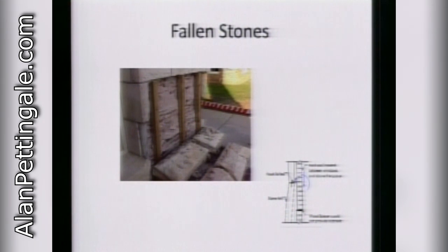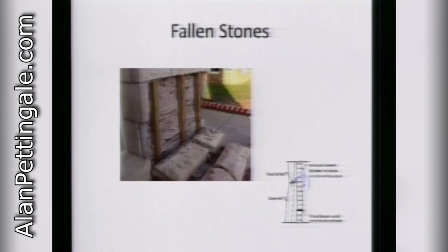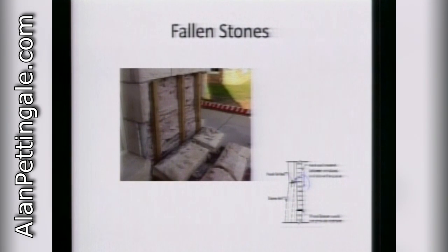The problem that happened some years after the reconstruction was that some of these stone water table elements fell off and had to be shored up. You can see from this picture that there was a cast stone anchor that failed — there was a slit in the top of the stone, but it rotated out and that's why it fell. Whereas it was not a problem for a hundred years, it became a problem just a few years after the reconstruction.